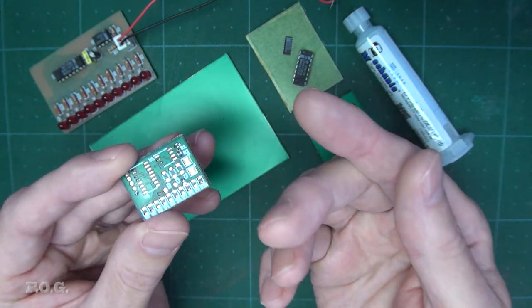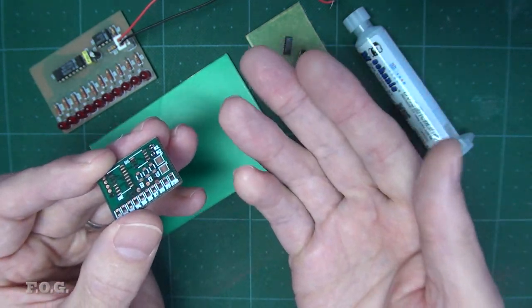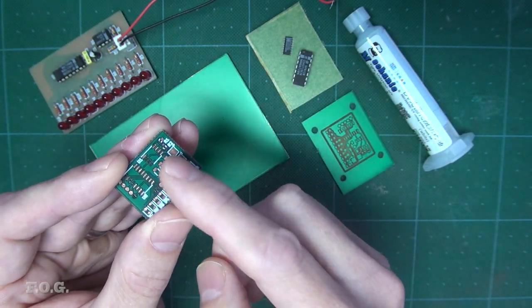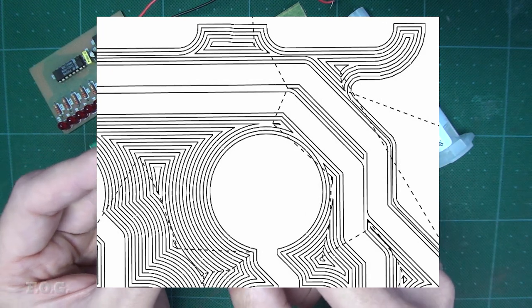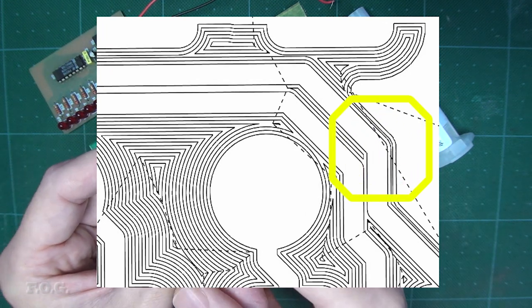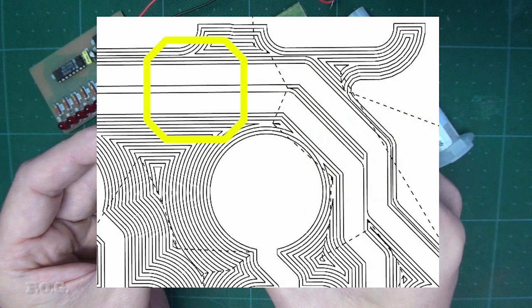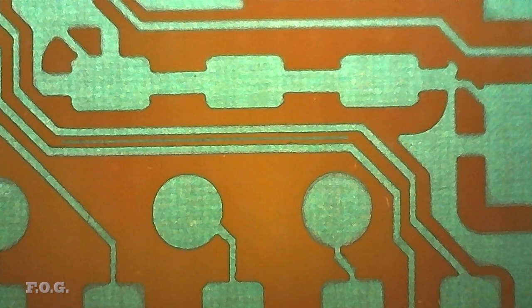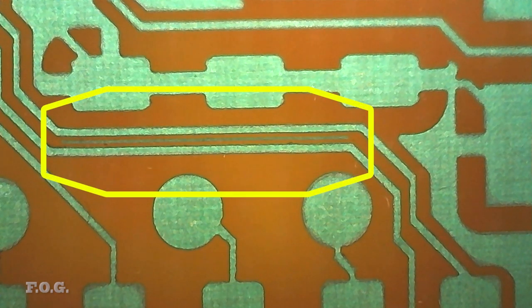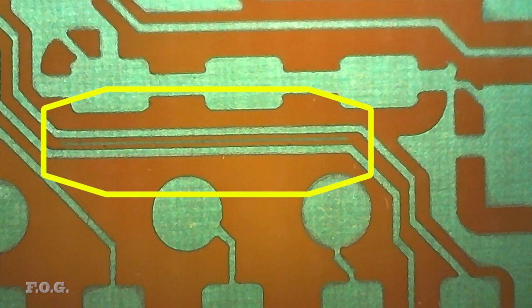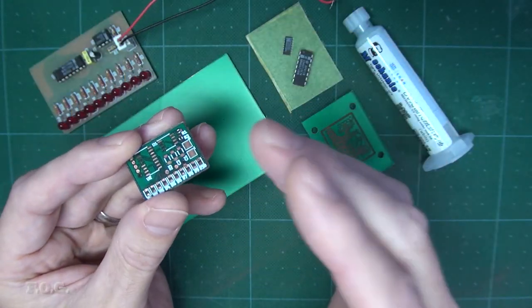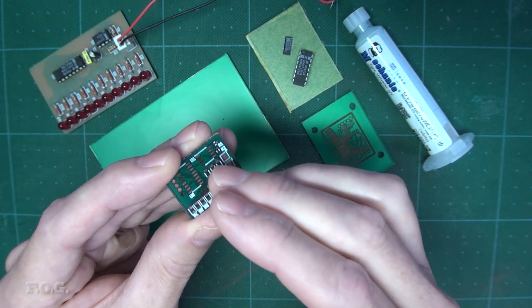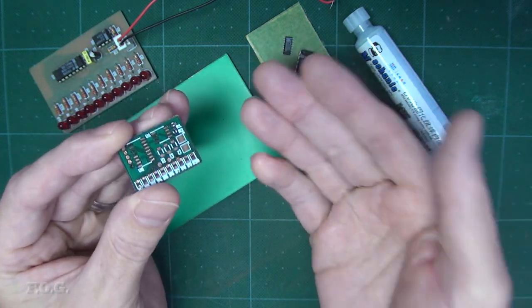And following this more precise approach, I also wanted to come up with a system to set the track widths and gaps so they make a much more neater burn path. Looking at the last G-code, you can see that sometimes the paths sort of overlap and sometimes there's even a bit of a gap between the two paths. Under the microscope, you can actually even see that this tiny line has been left as a result of that gap. So these tiny little deviations do have a real impact on the outcome, be it too much power being applied in one area or unwanted leftover resin lines as we see here. So let's fix this by coming up with a system.